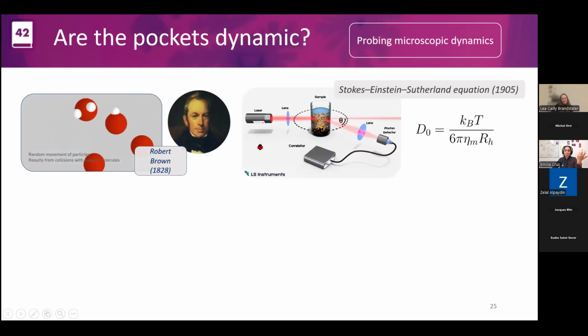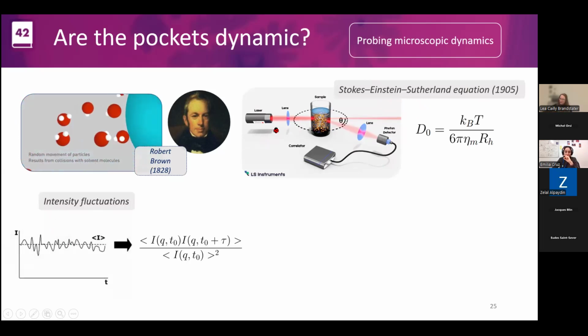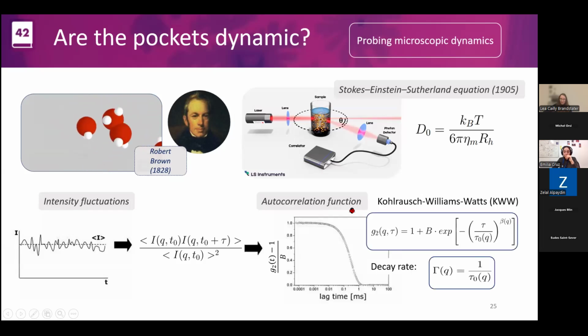So then, just because of this information, if you irradiate a sample that contains these Brownian moving particles with a laser, and then you record the fluctuations of the scattering, you can get information about the size of your particles, for example. And this is the Stokes-Einstein-Sutherland equation that allows us to compute a diffusion coefficient by just observing the intensity fluctuations of this laser, and then we build a correlation function, an autocorrelation function. So in time, as the experiment goes by, your structure will be shifting in terms of position of the particles. At some point, the particles will be completely at different positions, and everything will be completely different than it was. And just by seeing how fast this changes, you can already get an idea of the size of your particles and the type of diffusion.